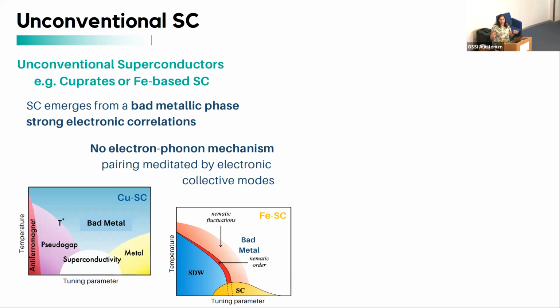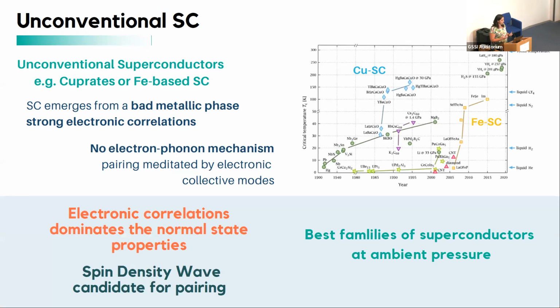I don't want to enter into the pairing mechanism because it's not actually the topic of the talk, but just to say that it's not electron-phonon and that the metallic state from which we start is a very bad metal. So I'm here talking about electronic correlation, possibly spin density wave as a candidate for pairing. And still, these are the best families of superconductors at ambient pressure, as you can see from this table. Yes, we are very far from the critical temperature of our hydrides. But the point is that, as I think Peter was mentioning yesterday, I don't think that room temperature Tc should be our only focus. I think that having a reasonable Tc with other important qualities should be reasonably important.